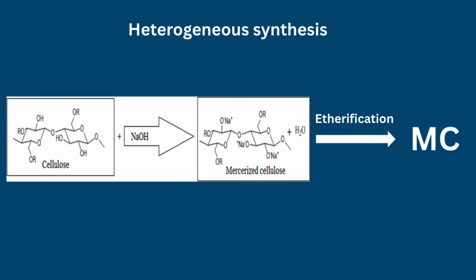Heterogeneous synthesis. The dominant commercial process performs etherification within swollen cellulose fibers. Because cellulose remains in the solid state, hydroxyl accessibility is uneven, resulting in heterogeneous substitution patterns containing highly methylated domains. These localized hydrophobic regions promote strong thermogelation and are characteristic of commercial MC grades.